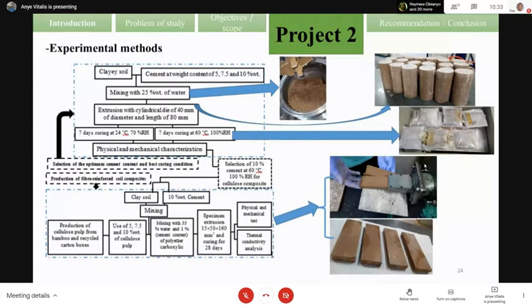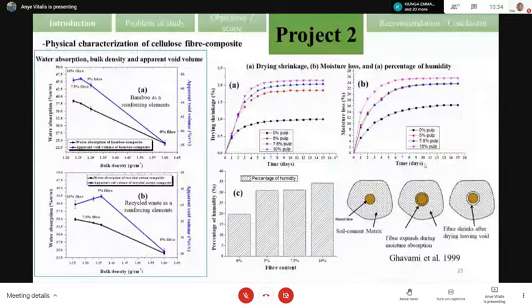Now we vary the proportion of the cellulose fiber, from the recycled fiber and the virgin fiber, from 5 to 10%, and now we produce the prismatic composite for physical, mechanical and thermal conductivity analysis. What is the result of the physical property?